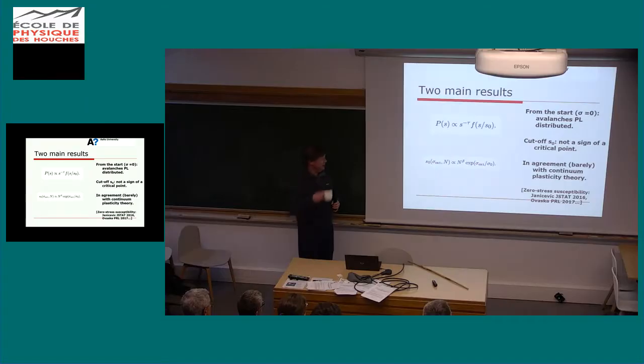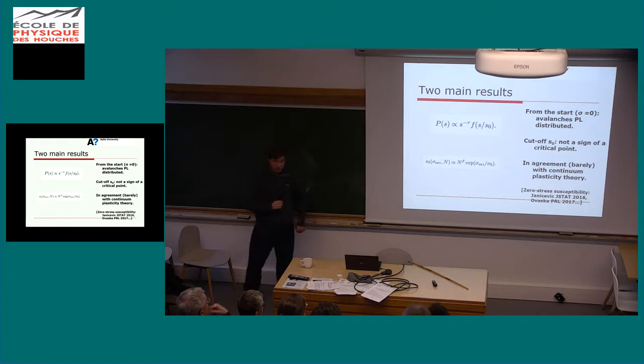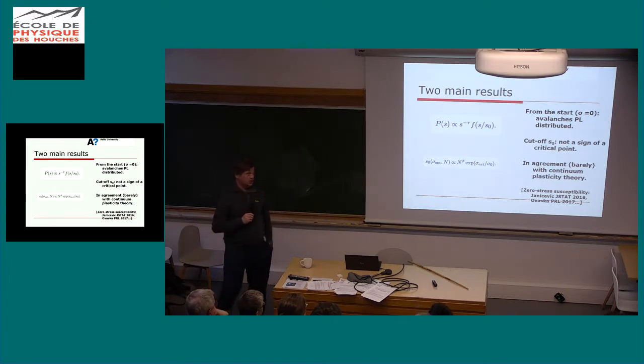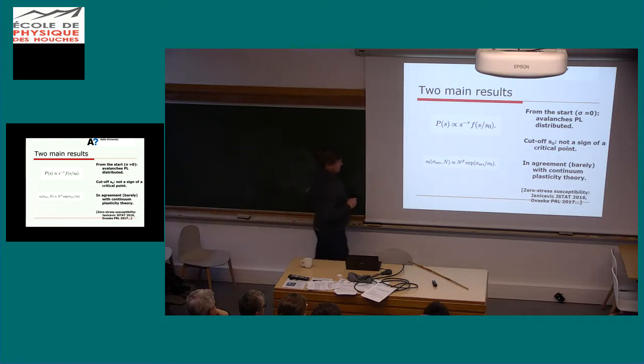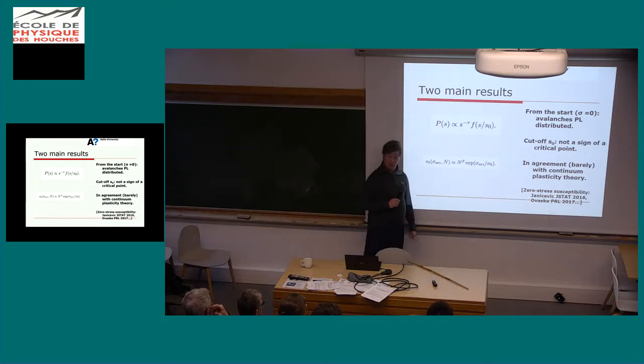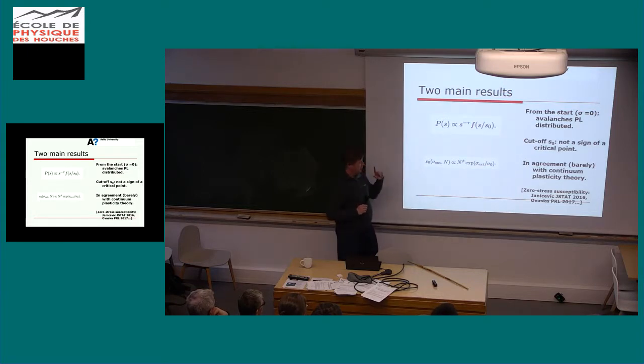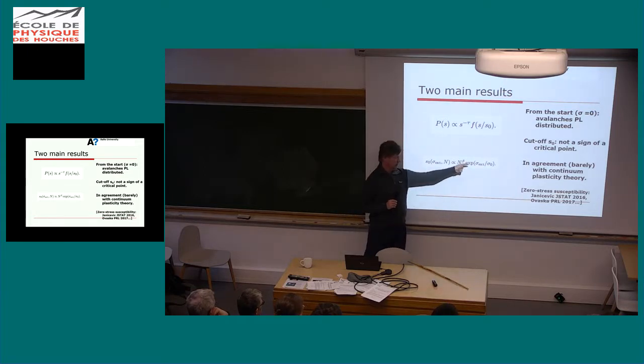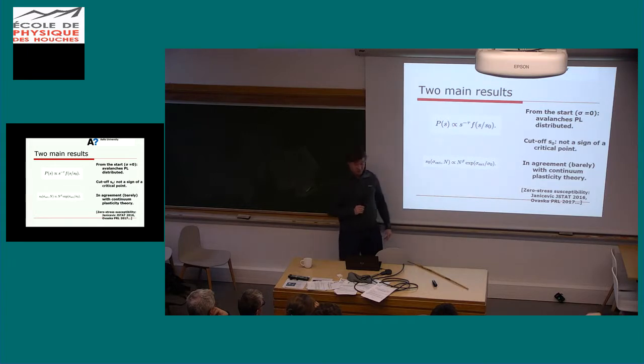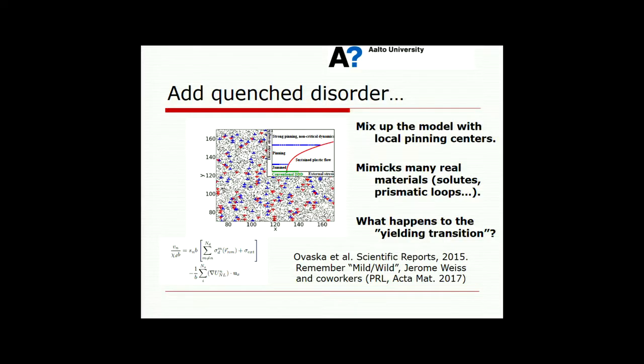This is what I'm saying here. You recover criticality. At least you can fit the data in such a way that these avalanches have a power-law-like behavior with a cutoff, and this cutoff scales in such a way that it looks a little bit strange. But you should remember which way it looks strange. And if you look at, for instance, the typical avalanche size in this system as a function of the number of dislocations, you see that it gives you a value which is reasonable; it doesn't diverge faster than the system size would.